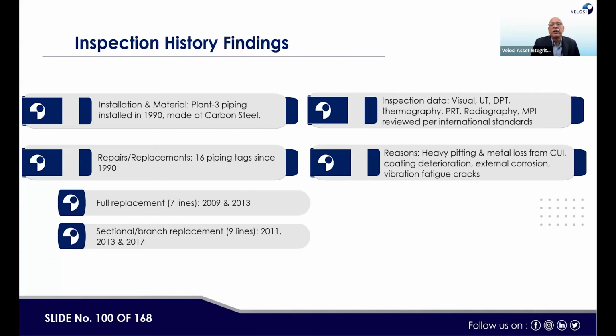Here, inspection history findings: the facilities were installed in 1990. Then we got the inspection data, like visual inspection, UT, DPT, thermography, PRT, all kinds of inspection results were collected and reviewed, and the kinds of defects which were there, for example heavy pitting, metal loss from CUI, coating deterioration, external corrosion, and vibration fatigue cracks could also be one of the troublemakers. Here, repair or replacement: 16 piping tags since 1990 were either repaired or replaced. Then full replacement of 7 lines from 2009 to 2013. Then sectional branch replacement of 9 lines in 2011, 2013 and 2017. So all this history was reviewed.